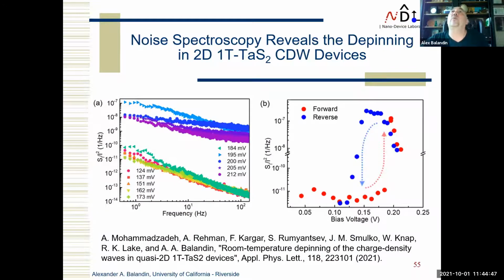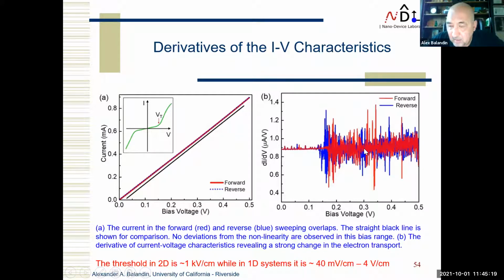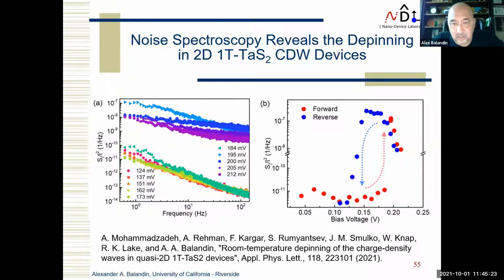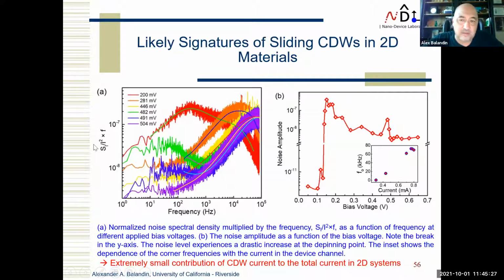And we also used the power of low frequency noise spectroscopy. We see that noise at this point increases tremendously. It also evolves from 1/f to having some bulges. You can see this is now noise spectral density as a function of bias voltage, at exactly the same bias voltage. We have this huge increase, several orders of magnitude, because there is a break in the scale. The hysteresis and everything coincides with what we see just by the derivative of the IVs. We thought that must be something related to charge density wave moving in two-dimensional materials. This is now noise spectral density multiplied by frequency to get rid of the 1/f background. We now clearly see some Lorentzian bulges which start moving, and their motion also approximately scales with the current.